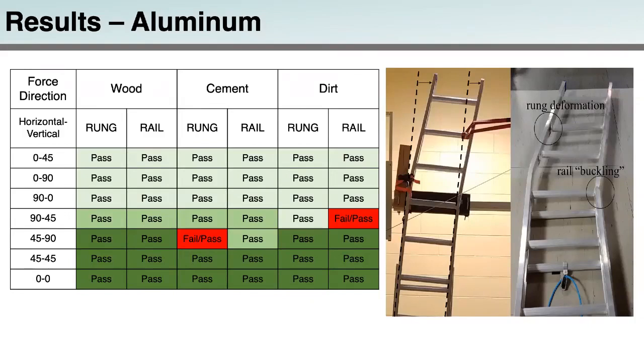So the first testing condition that produced a failure was the loose earth ground condition, the rail tether, so this would be the tether around both side rails of the ladder, and the 90-45 force direction. The second condition that produced a ladder failure was the dry cement ground surface rung tether, so this would be the tether just around the rung, and the 45-90 force direction. So again, it was this 45-90 degree off force direction that was really damaging to the aluminum ladder.